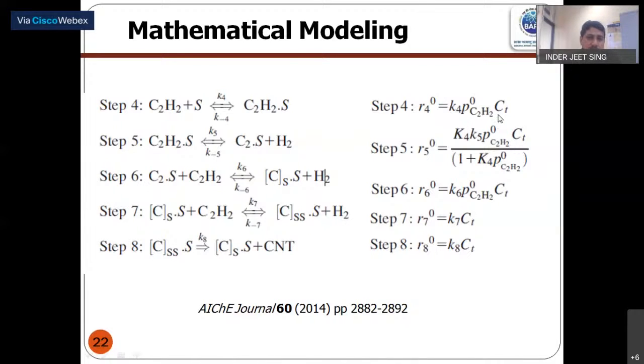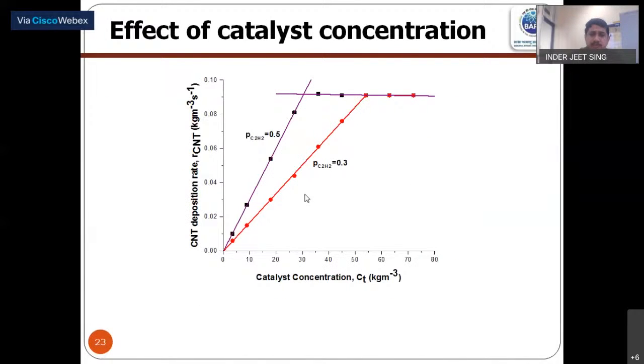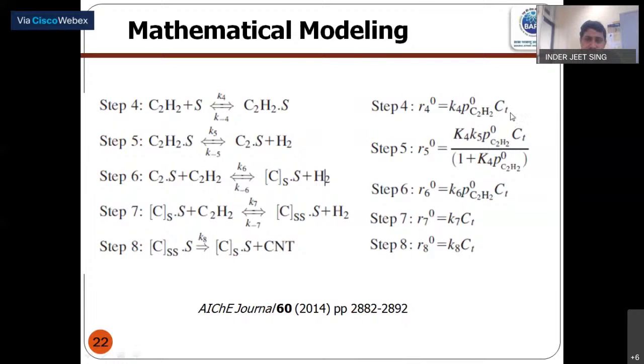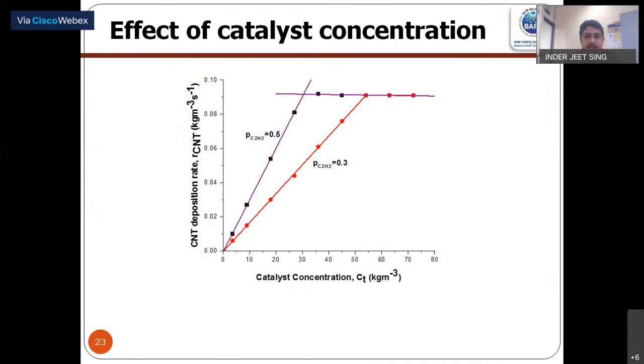We can have the mathematical equation related to that, and considering each step as individually rate controlling, we can find the final equations like this. Why is this required? Because finally we need to plot the experimental data and see which equation it fits, and then we can say, this particular step is the rate controlling step. In all these equations, CT means catalyst concentration, and they vary linearly with catalyst concentration, which can also be seen in this graph. If we vary the catalyst concentration at various partial pressures, it is a linear variation.